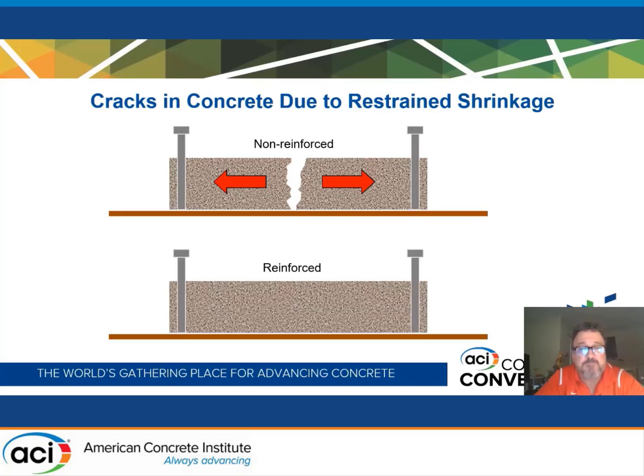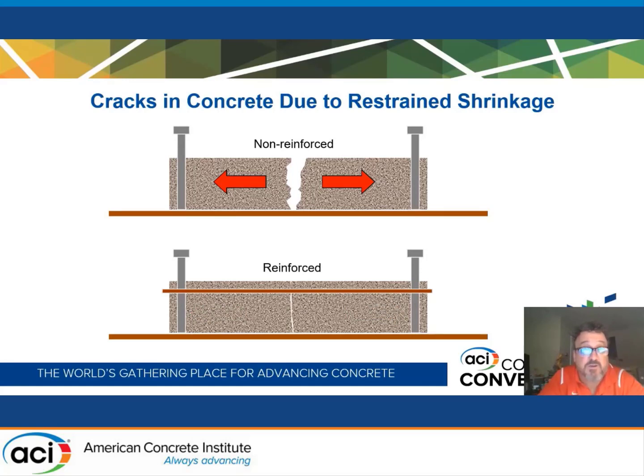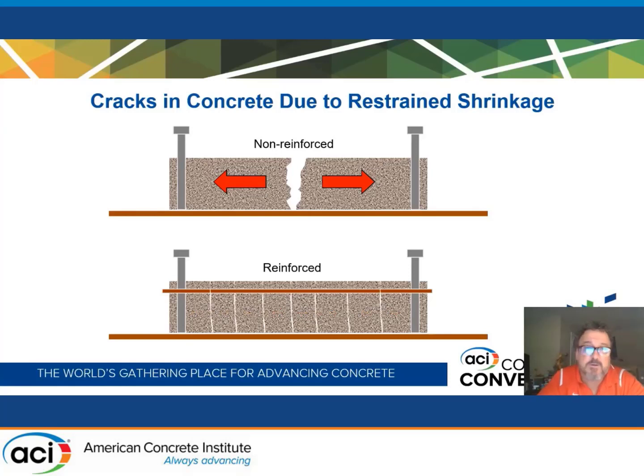In the same situation for a reinforced slab, the reinforcement is in the slab — positioned near the top, which is the tensile zone for a slab on ground. Once that initial crack occurs, the steel is engaged. Unlike the unreinforced slab, this doesn't fully alleviate the tensile stresses. Now you've got two pieces of concrete with restraint to continued shrinkage, so you can get more cracking — then four pieces, and more cracking still. The higher the steel percentage in your concrete slab, the more cracks you'll get, though each crack is tighter. We want to stay at a tenth of a percent with ACI 360 joint spacing recommendations to avoid visible random cracks.